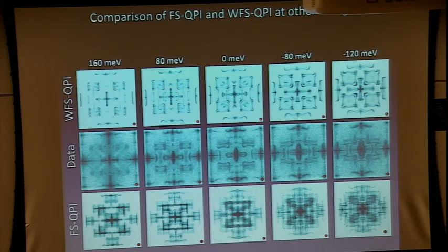I'm sorry? It depends on where you are in the Fermi surface. And this is precisely what's interesting about this experiment. So you have these Fermi arcs, and as you move around them, at different places, if you put an electron into them, you can think of it as a lifetime. The lifetime of the electron on the surface varies as a function of k. And this experiment is probing that, because it just looks at the interference, and whichever q, initial and final, where the lifetime is short, we don't see it.